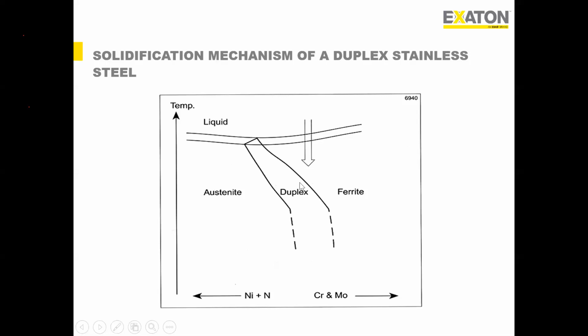As I mentioned, solidification is basically a function of time. So it is in a liquid phase, then it transforms into delta ferrite or ferrite, and if we allow more time to solidify, it will transform into austenite. Now, if we don't allow the liquid weld metal to be in the liquid state for a longer time period, or on the other hand, if it solidifies very quickly, it forms a ferrite from the liquid, but it does not get enough time to transform into austenite. So we will get the end result of a lot of ferrite and less austenite.